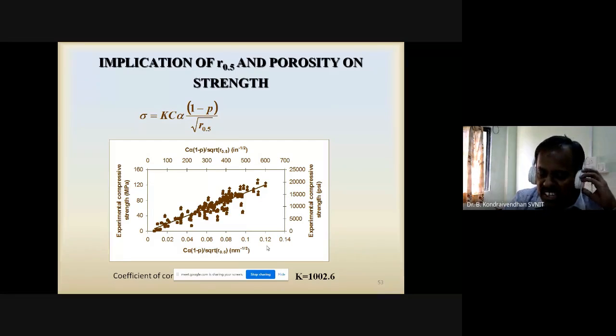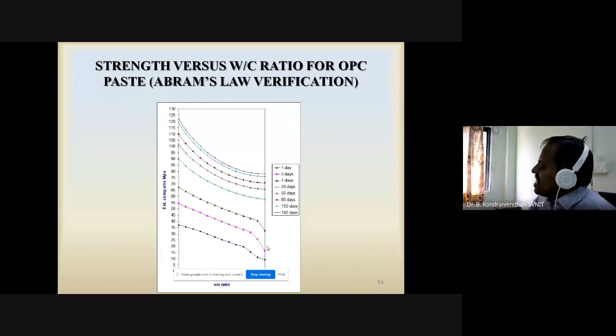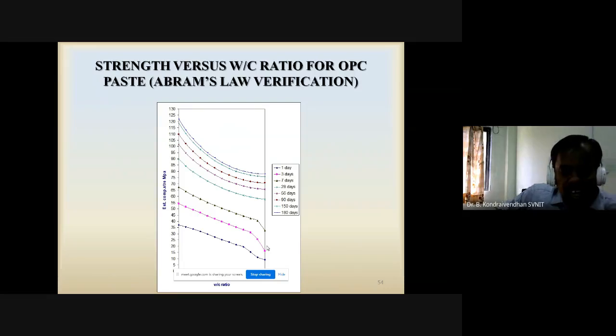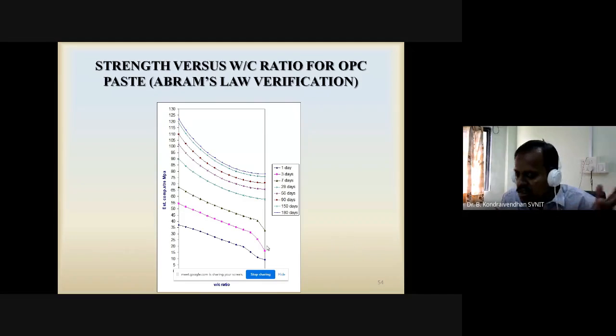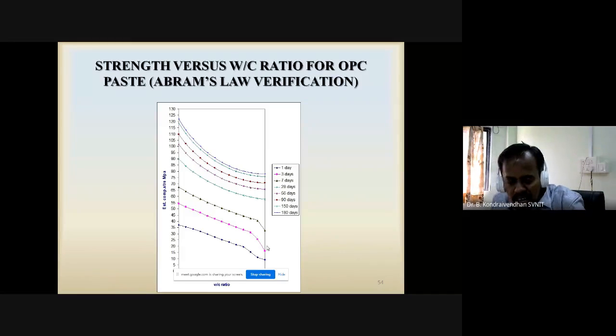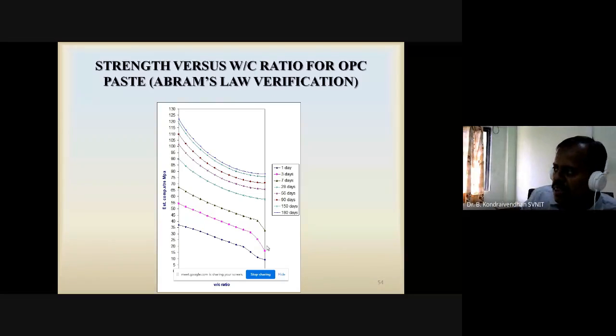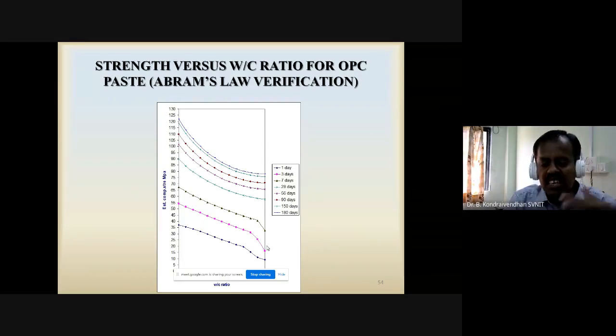Then again we have to check it, because we know Abraham's law: strength is inversely proportional to water cement ratio. So now we can also estimate the compressive strength for different water cement ratios and different curing ages using this relation, and plot the estimated compressive strength against the water cement ratio. That is also behaving in the same manner. But if you look at the graph for 1 day, 3 days, and 7 days, it is not very smooth. Why is it happening? Because self-desiccation is happening at the early ages, and that's why the pores are only gel pores. That's why it shows a somewhat non-smooth curve. Otherwise, it is showing the same curve. That's how we can prove that our prediction formula is matching with the existing theory.